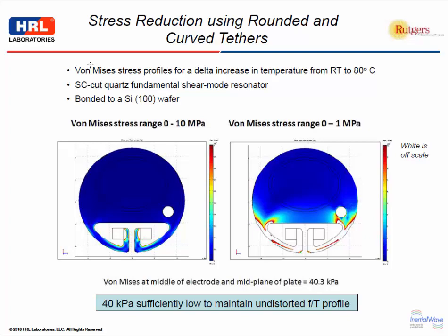This is a stress plot with a range between 0 and 10 megapascals. And the white is off scale, so the white is over 10 megapascals, but you can see it quickly drops to a fairly low level in the active region. This is a wider scale from 0 to 1 megapascal, and you can see you're still very low in the active region, so you've got all the stress drop along the tethers. It's actually about 40 kilopascals a variation between room temperature and 80 degrees in the active region. And we found for our previous VHF parts that if you're in the 10 to 40 kilopascal total stress range, it won't rotate or affect your FT profiles. So that was the design we picked.